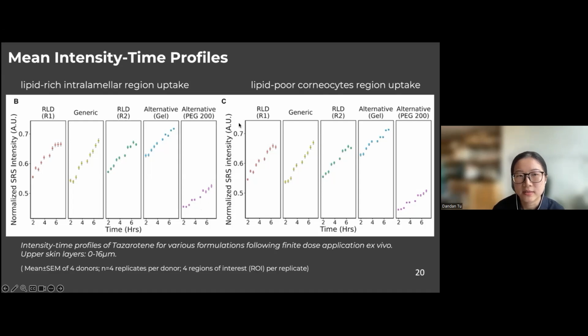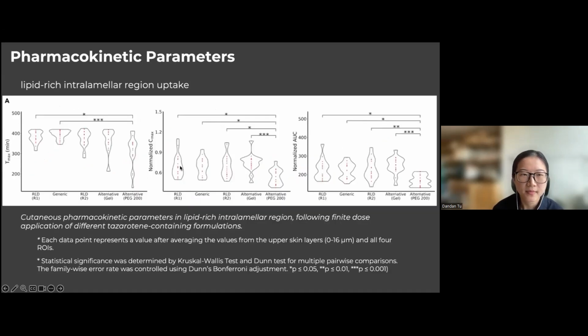And in this study, for the lipid-rich and the lipid-poor regions, their intensity time profiles are very similar. We don't see a very distinct difference between the two regions. And then using the profile, we can calculate the Tmax value, Cmax value, and AUC value. We can use those values to do a pairwise comparison.